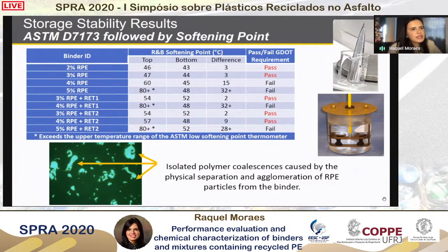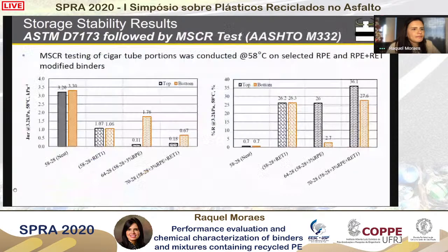And as you can see here in the green picture, we have a UV microscope micrograph, and we can see the very bright green parts that are indicated with the yellow arrow. These are isolated polymer coalescence that were caused by physical separation between the binder and the plastics. This is for the blends with 5% of recycled polyethylene. So you see, you do not have dispersion of this material within the asphalt binder whatsoever.